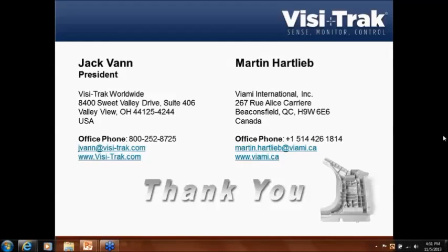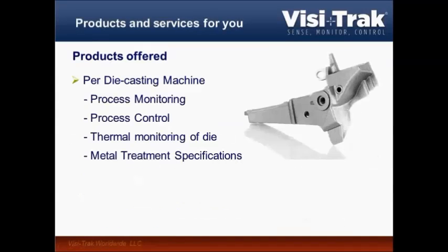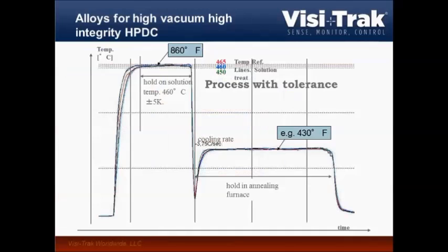What is meant by precision quenching? Precision quenching in this case means, actually I could go back to that slide that was not far back. Here we have this. In order to avoid warping of the part, distortion of the part, you want to come out of solution and quench it at a certain cooling rate that you want to keep constant all the way down, and you want to apply precision air. So you want to blow air onto the parts, not quench them in water, so they actually get quenched from the bottom to the top, for example. That is meant by precision air quenching in this case.